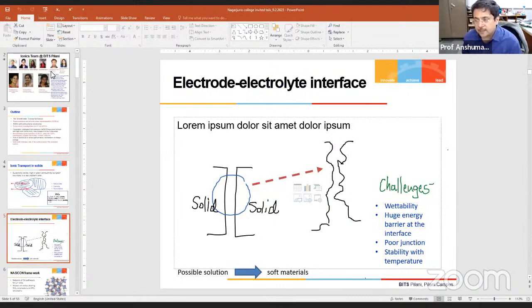Another issue is the electrode-electrolyte interface. Even if we know how we make a PN junction, it is not that we have a P and an N and we join them and make a junction. A PN junction essentially is in one semiconductor single crystal. On one side you grow the N type impurity using diffusion, on the other side P, and then you talk about the PN junction, where again there is a potential barrier. But here we talk about two solids coming to each other, making an interface, and through that interface we expect fast ionic transport without any potential barrier. So there is a challenge. You have a challenge of wettability, a huge energy barrier, and poor junction, in the sense that you cannot utilize the complete surface area. Both surfaces have their own natural roughness, and there is a problem.